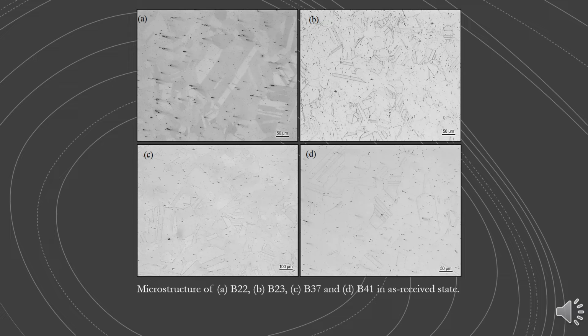In as received conditions, all the 4 alloys show austenitic structure with visible twins with an average grain size of 50 to 200 micrometers, as shown in this slide.